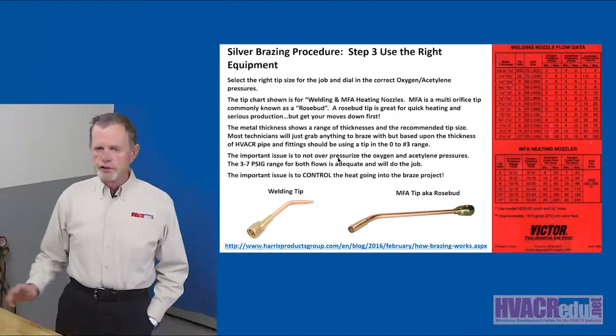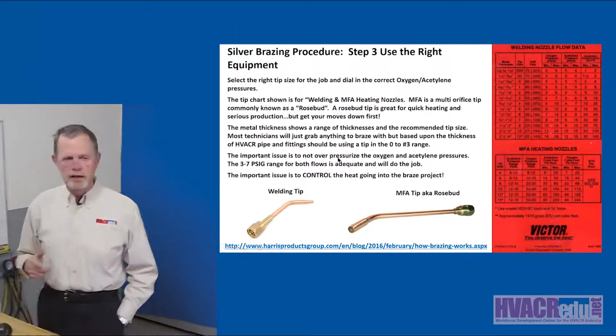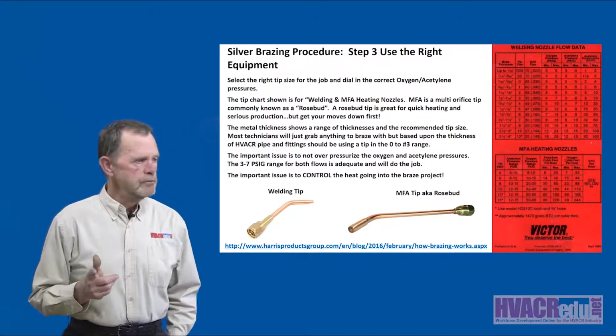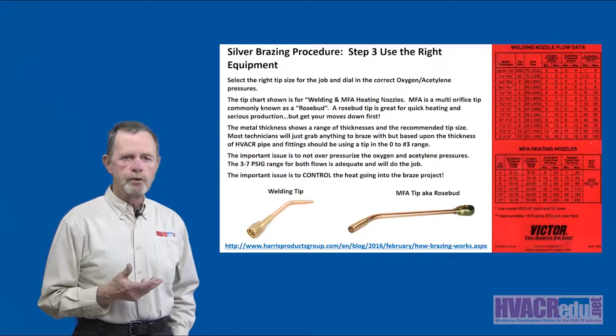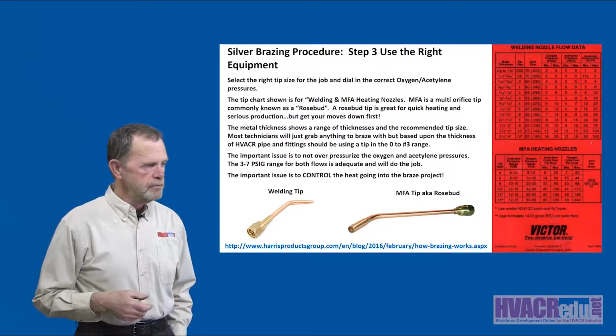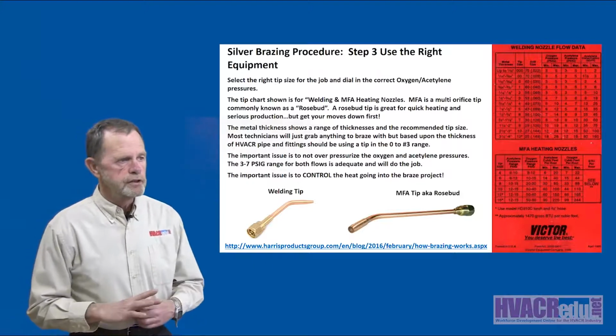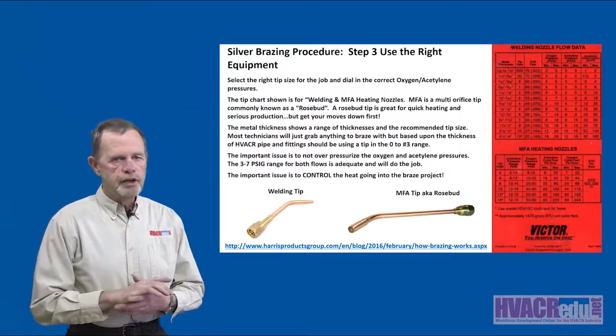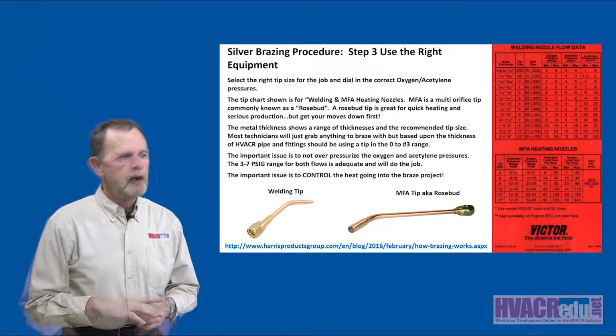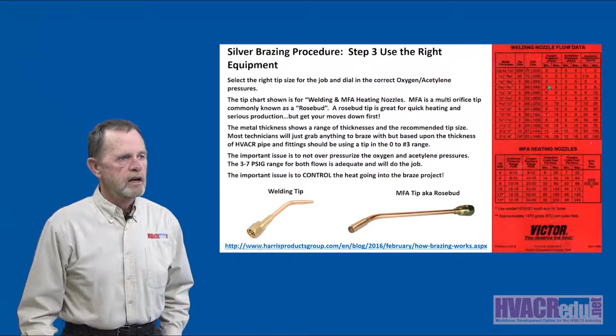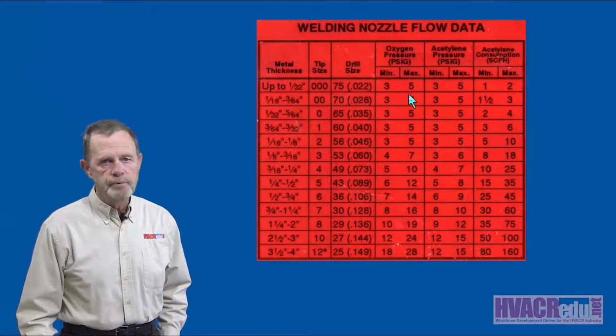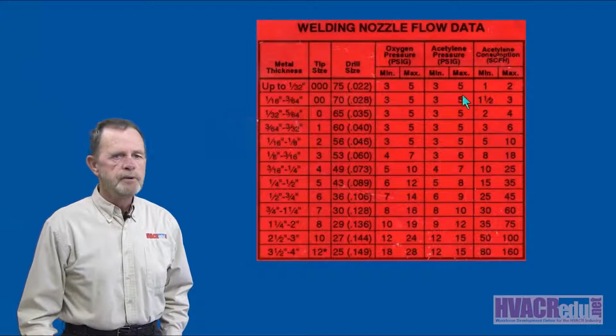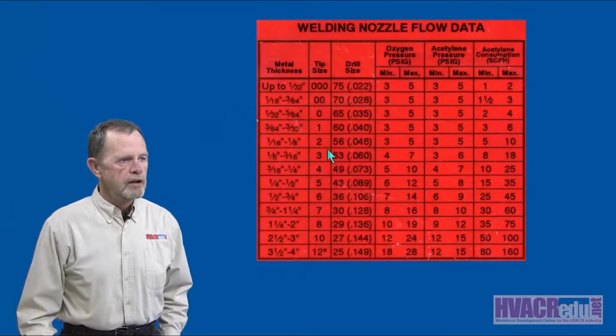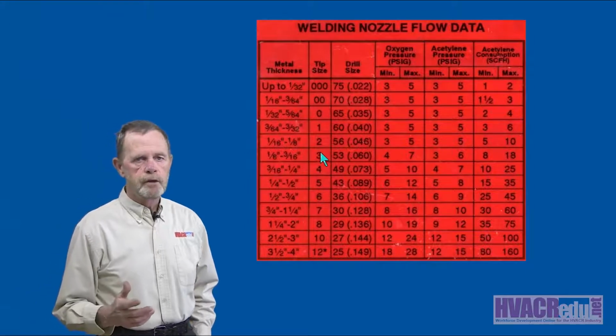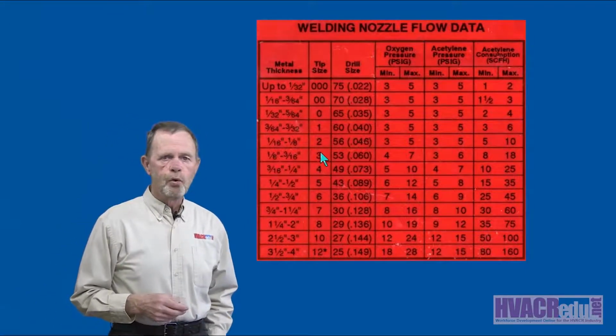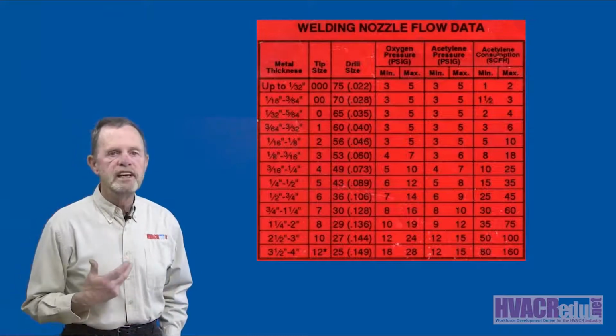Okay? The important issue is not to overpressure your oxyacetylene. The 3 to 7 psi range, for both flows, is adequate and will do the job. I know most guys will grab a tip, it doesn't matter what tip it is, they'll throw it on the torch, and they'll crank the pressures up. You don't need to go there. 3 to 7 psi. As you can see over here in the tip chart, I have 3 to 5 psi on the oxygen side, 3 to 5 psi on the acetylene side, all the way down here until I get to tip size number 3. So you're not really dealing with a lot of fuel pressure or oxygen pressure on your torch. You don't need that much pressure.